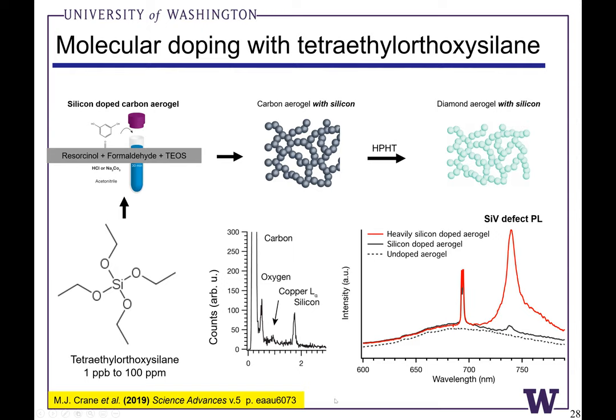If we dope at parts per billion or parts per trillion levels, we can see just a minute amount of emission. And if we really dope the heck out of these things with, say, parts per million plus levels of silicon, effectively, we could start making silicon carbide or other allotropes or polytypes of silicon carbide with this approach. But you can see this very pronounced silicon, the negatively charged silicon vacancy emission from these doped materials. So really excited to be able to control that.